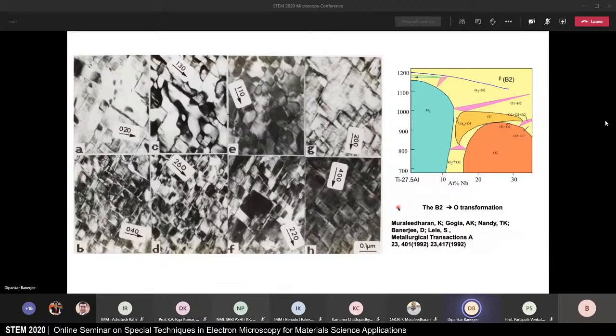And this involved a slightly different kind of microscopy. It involved the microscopy that I alluded to earlier, of looking at the interaction between the diffracted beam and the defects in the system, the coupling of the diffraction vector and the contrast that you get in the microstructure as a consequence of the defects existing in the system. And so he was able to define, in the course of this transformation, the various different kinds of faults that occurred, various antiphase boundaries, for example, as shown in these images of contrast with different diffracting vectors. And he was able to completely define the mechanisms of this transformation that allowed us to control the microstructure in a way that we wanted for mechanical properties.